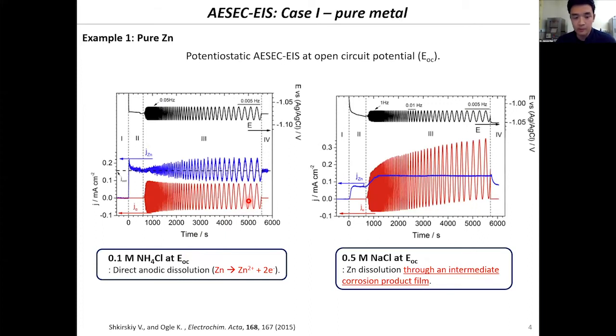What I'm presenting now is not the first time this was tried. It was tried by Kevin's previous student, Slava Shkirsky. They tried this coupling for a simple system, in this case zinc at open circuit potential. On the left side, you are seeing ammonium chloride at open circuit potential. Zinc dissolution shows a nice oscillation correlating to the oscillation of the total current density. So we can expect that the oxidation of zinc in this condition is direct formation of the cations.